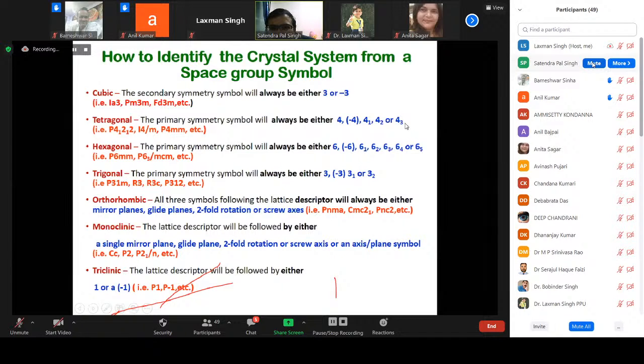In the tetragonal, we will have a -4, 4, 4_1, 4_2, 4_3, etc. on the primary position. In the hexagonal case, we have a -6 or 6, 6_1, 6_2, 6_3 on the primary position. In the case of trigonal, we have -3, 3, 3_1 or 3_2 in the primary position. In orthorhombic, we can have a mirror plane or glide plane, or a two-fold rotation or screw axis, simultaneously on each position, primary, secondary, tertiary; all of the positions are occupied.